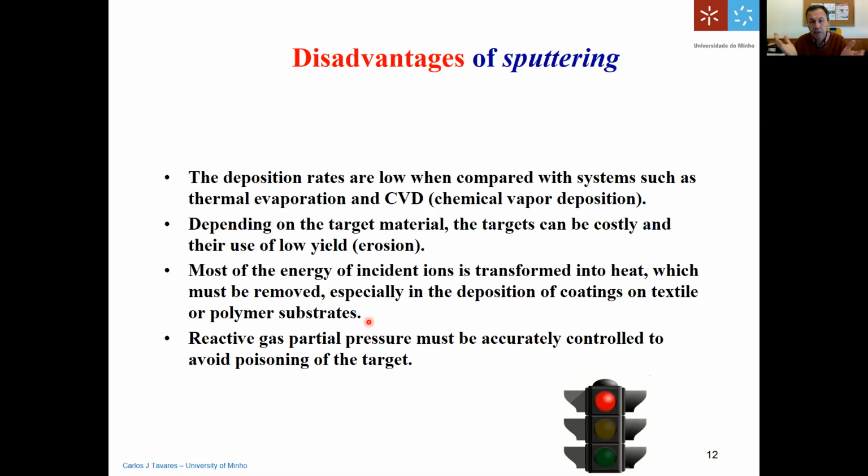Depending on the materials. But for example, a titanium target with a 4-inch or 10 centimeter diameter and 6 millimeters thickness can cost about 250 euros. And they last a long time. In some cases, these targets can last 2-3 years just for laboratory work. While others are more expensive. For example, targets that can produce transparent conductive oxides, like ITO, indium tin oxide, can cost about 800 euros for the same size, about 10 centimeters in diameter and 6 millimeters thick.